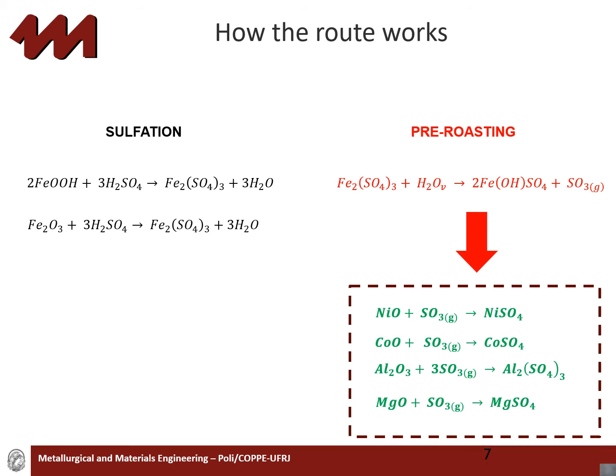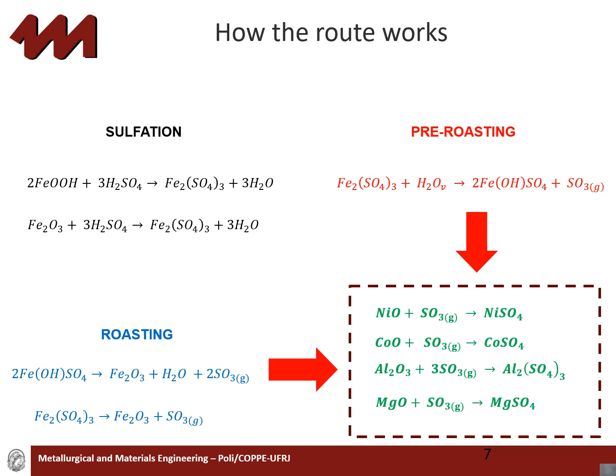So, how does the route work? First, the sulfation. The main minerals present in the ore are goethite and hematite. They will react easily with the sulfuric acid to form ferric sulfate. Due to their instability in the temperature range used, the trivalent sulfates like the ferric sulfate and aluminum sulfate will decompose, releasing SO3 during the pre-roasting and during the roasting steps. This sulfur trioxide will react with other metal oxides present in the ore sample. The temperature range evaluated tends to increase the formation of metallic sulfates, such as those of nickel and cobalt, which are more stable than iron and aluminum sulfates.